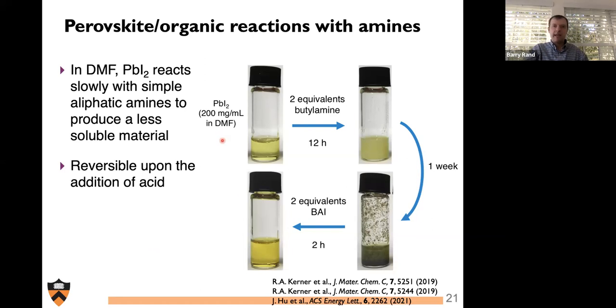And if we take lead iodide and DMF and add butylamine to it, we can see almost instantly the formation of a cloudy solution, which turns rather turbid and dark after about a week, but this type of solution can even be turned back toward the initial starting point by adding the equivalent acid, butylammonium iodide in this case. So this had something to do with the interaction between lead-2 and amines, and certainly something regarding the pKa of the solution.